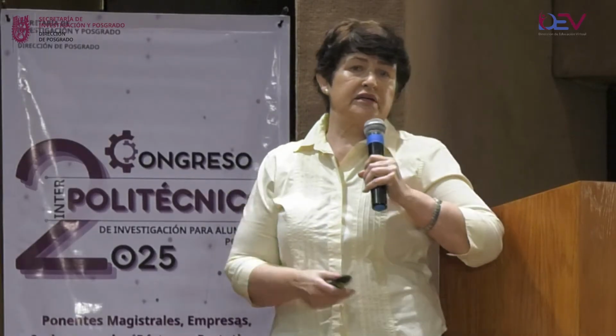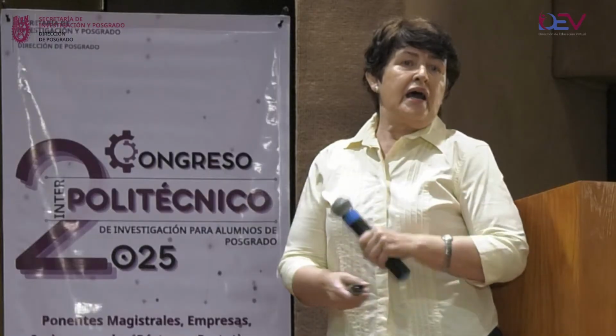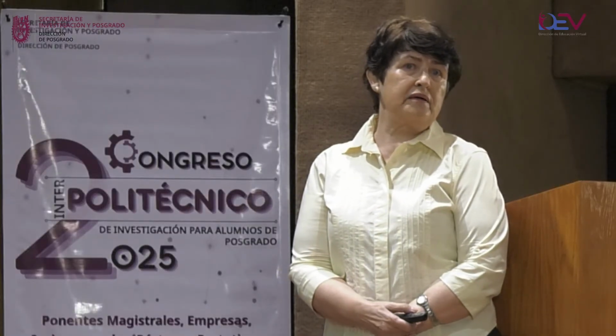So something like near 10^19 to 10^21 is the electron concentration which it was possible to receive, and after this concentration of electrons in a transparent oxide, the self-compensation process starts. So our task was to shift the start of the compensation process to the area of higher concentration. How is it possible to do this?